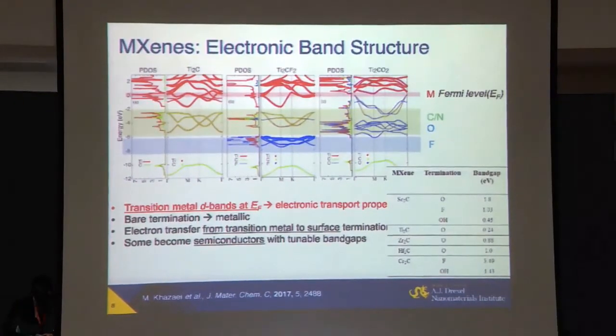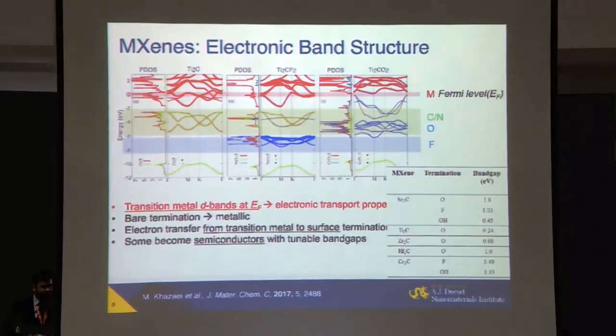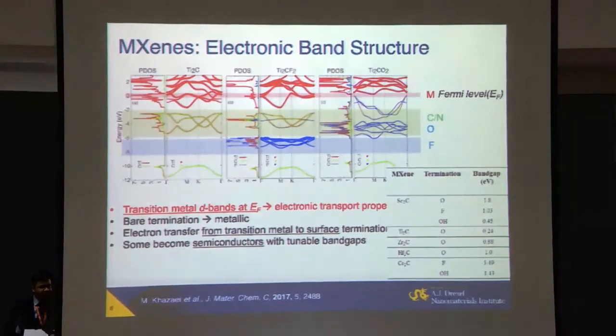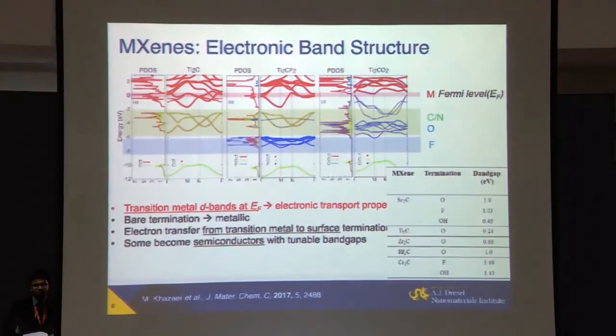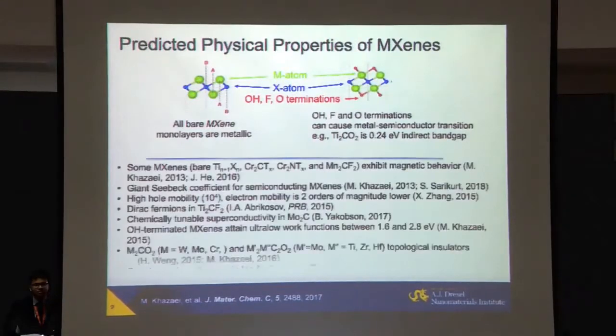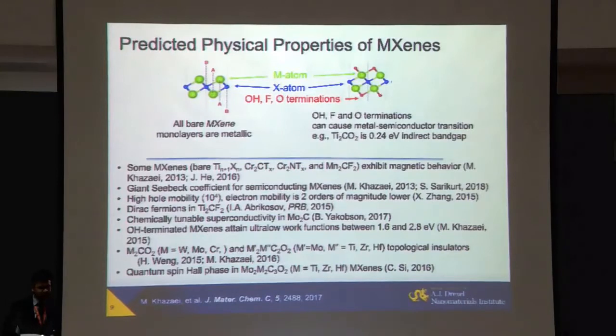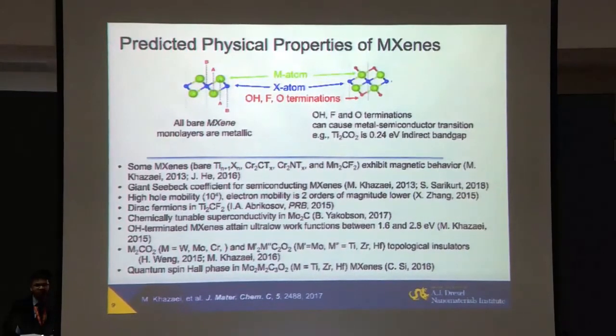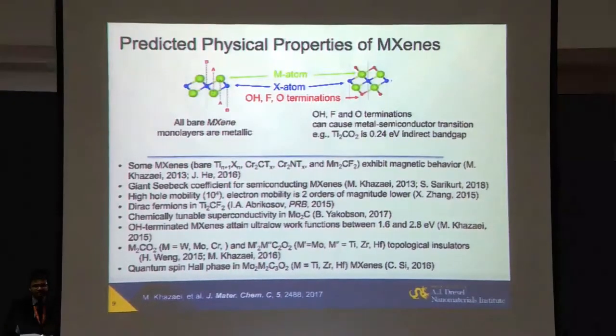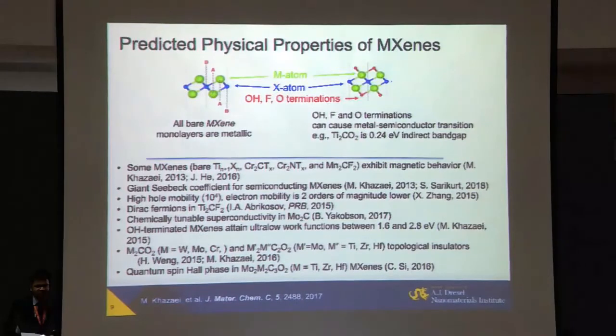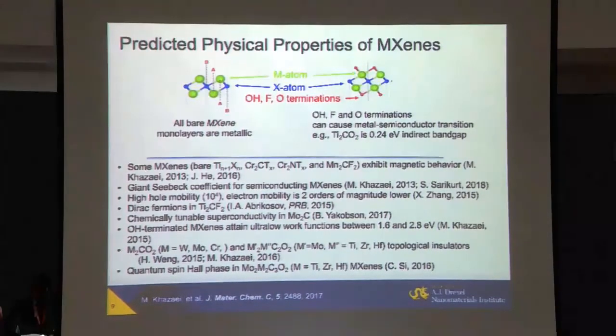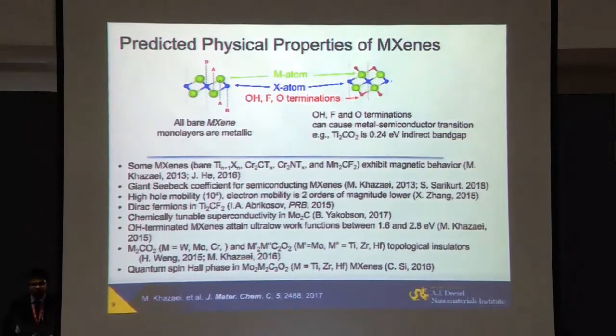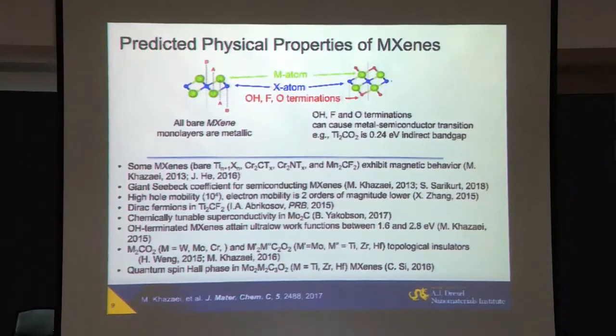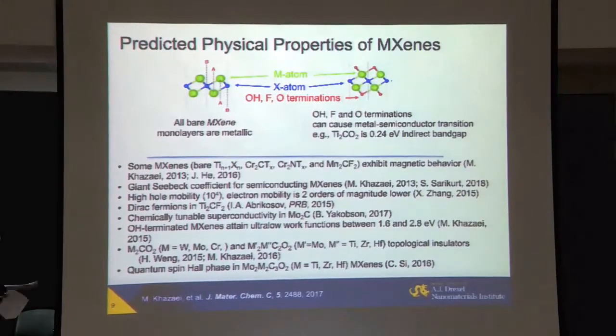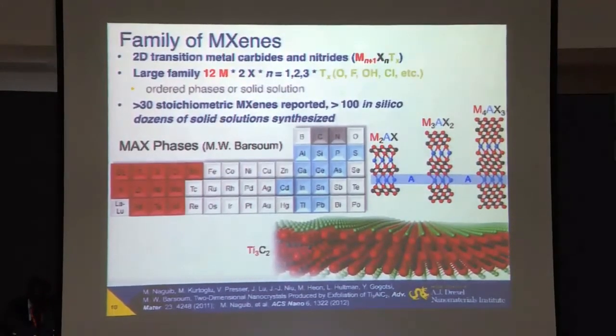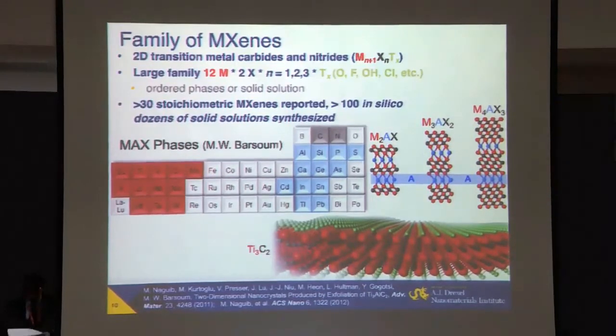Some MXenes, as this table shows, have actually been predicted to be semiconductors, but they have not really been much studied yet because there are plenty of semiconducting materials available in 2D. Still, I'm pretty sure we'll find some interesting properties there. So, there have been many other properties predicted. Magnetic MXenes, we're exploring two-dimensional magnetism now in MXene. Giant Seebeck coefficient means potentially useful thermoelectric material among semiconductors. Dirac fermions have been predicted in titanium 2C terminated with fluorine, so cones like in the band structure of graphene. Ultra-low work function, actually work function tuning is already used in perovskite solar cells, and topological insulators, many, many others here. So, those materials have this wealth of attractive properties.